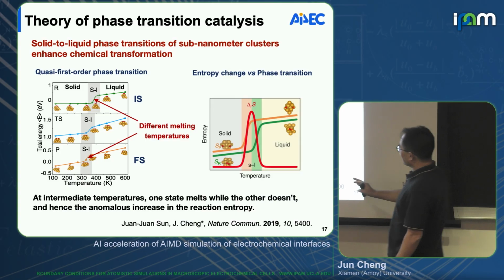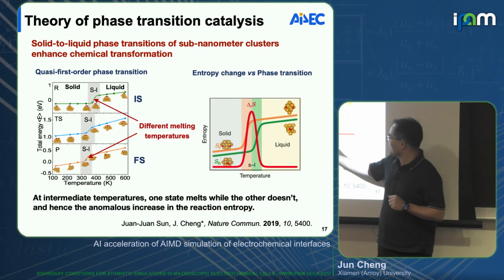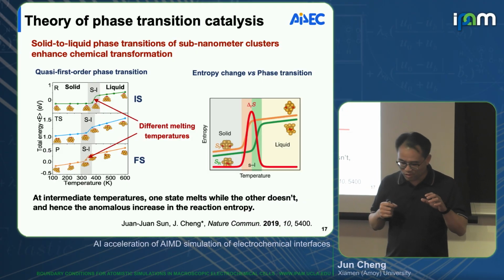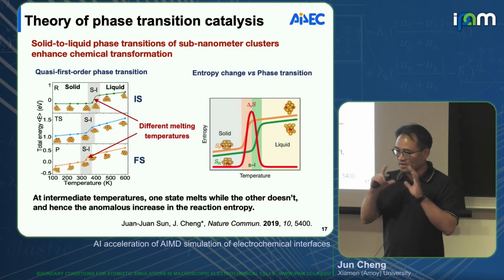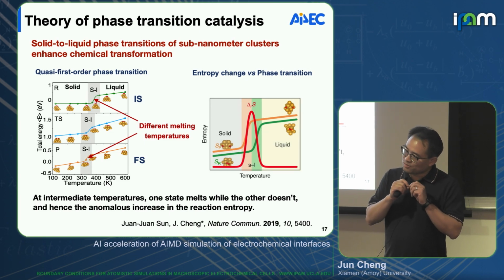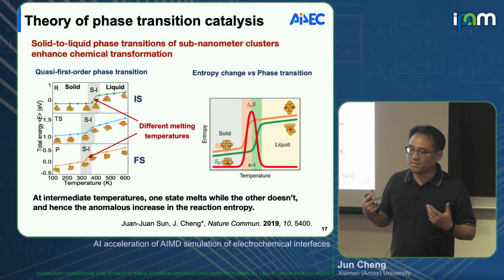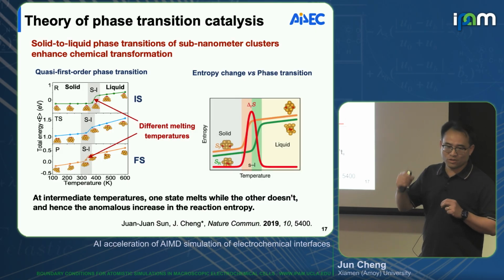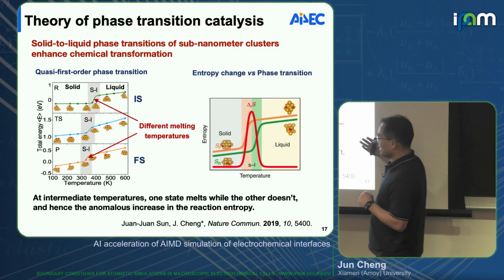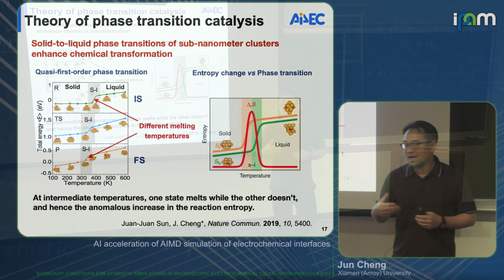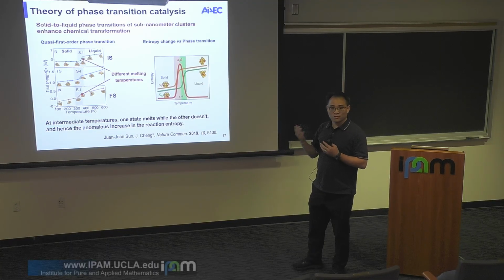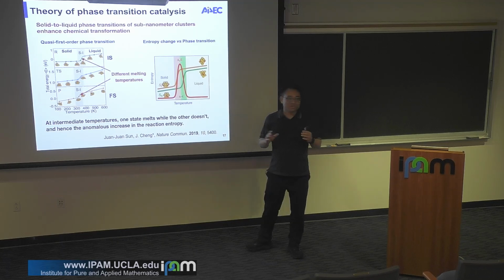goes down. Following this range, at this temperature range, the reactant, when we have an oxygen molecule absorbed on top, is a solid, including the cluster. Along the reaction path, when the two oxygen atoms are being pulled apart, the whole cluster starts to melt. That will lead to an entropy increase and then a free energy decrease. So to me, this anomalous increase in the reaction entropy due to the phase transition is a new type of catalytic effect. Only after we use ab initio molecular dynamics to do the full free energy calculation could we capture this, right?